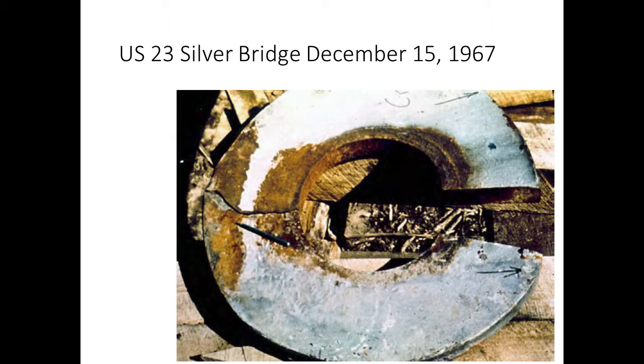This was sent to the National Bureau of Standards, and they did failure analysis on the bridge, and they determined that the initial crack was caused by corrosion cracking, and it ran in brittle fracture across the leg of the eyebar head there. The other thing that they found was the crack size was very small, only like 3 to 4 millimeters. And the Bureau of Standards said that there was no known non-destructive evaluation method that could be used to detect this crack.